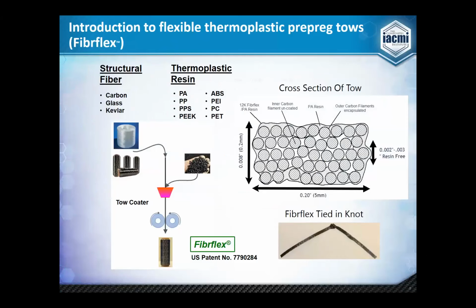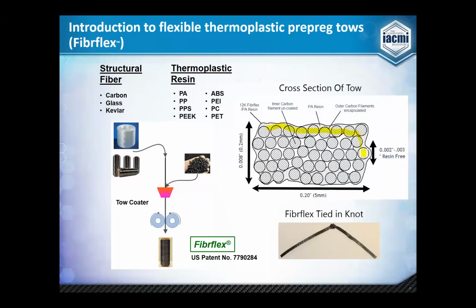The toe, if you look at here, pointer here, getting highlighter. If you look on the outside of the toe, the resin is impregnating basically just the outer portions of the toe, the outer 1/3, if you will. The inner 1/3 is unimpregnated. A typical carbon fiber polyamide toe would be approximately 0.2 inches wide, about 8 thousandths thick. The inner 2 to 3 thousandths is substantially unimpregnated. And what that allows is the toe to be extremely flexible.